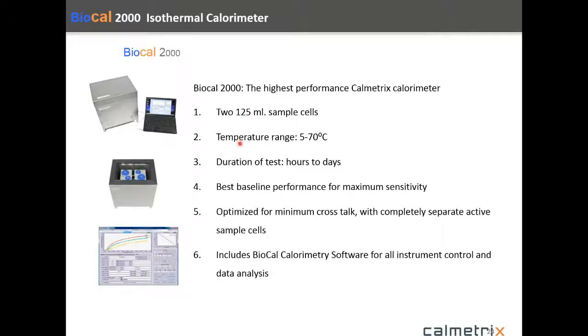Temperature range 5 to 70 degrees C. This is actually the same between both instruments. And the duration of test is anywhere from hours to days, only limited by the tests that you're doing. It's not limited as far as the instrument is concerned, and that's the same between both instruments. But the 2000 definitely has the best baseline performance, so it has the maximum sensitivity. So if you're looking for the absolute maximum sensitivity, then the 2000 is the best instrument. It has 2 individual calorimeters, so it optimizes for crosstalk, and that's why it has the best performance.